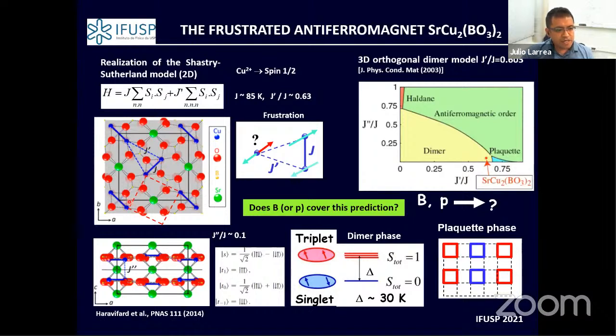Therefore, you can see there is a degree of magnetic frustration, because in this singlet, characterized by the intradimer coupling J, you simply have a singlet state, meaning an antiferromagnetic or antiparallel coupling.